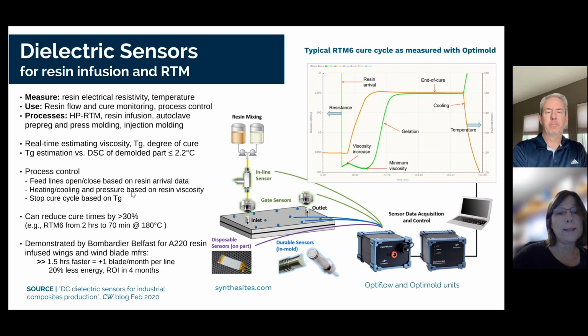Now, why is that important? Well, they've already demonstrated they can reduce the cure times on RTM6, which is kind of the current state of the art with RTM in the aircraft industry, and they've been able to drop those by more than 30%. That's really impressive. One of the examples that I pointed out in the blog I did on this was when Bombardier Belfast developed this infused wing process, part of their more recent development in the past few years was to look at using these sensors. And even though they're injecting and in the autoclave, they're able to pass those sensors through the autoclave wall. It was pretty impressive what they were able to get on that.